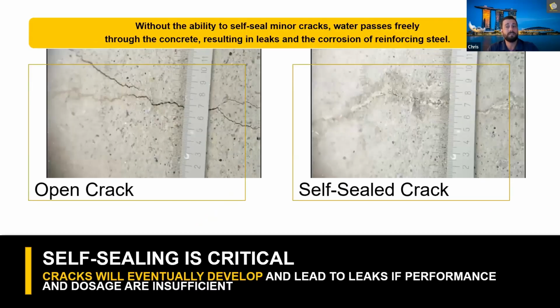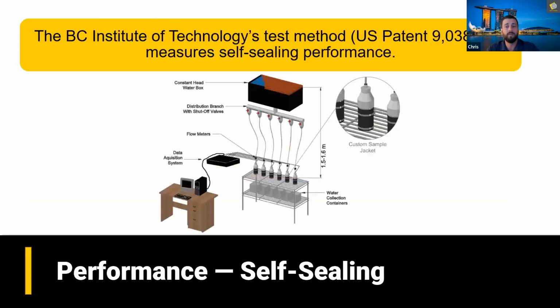Now, let's switch to self-sealing of cracks. We know that concrete cracks, as Jeff mentioned, ACI requires self-sealing for the life of the concrete. Using a crystalline admixture will increase the self-sealing performance. Much can be done to reduce the size and number of cracks in concrete construction, but over the concrete service life, microcracks are unavoidable. So if the crystalline concrete is unable to self-seal these cracks, water flows freely and not only creates leaks, but also creates corrosion. Little cracks turn into big cracks and deterioration of the concrete and reinforcing steel occurs. This is one of the most critical performance properties for waterproof concrete.